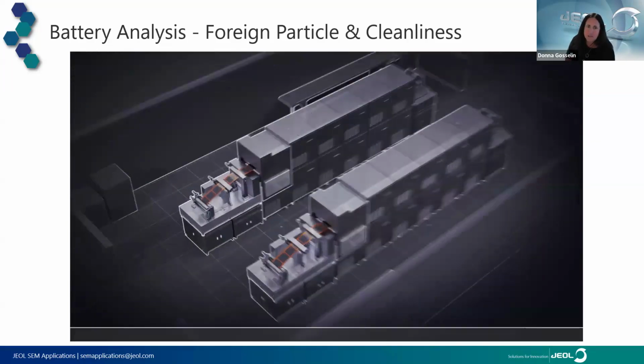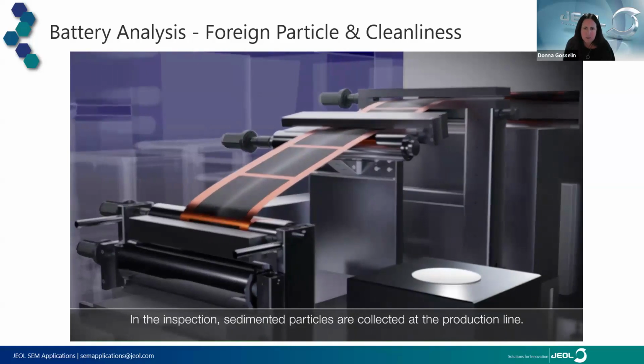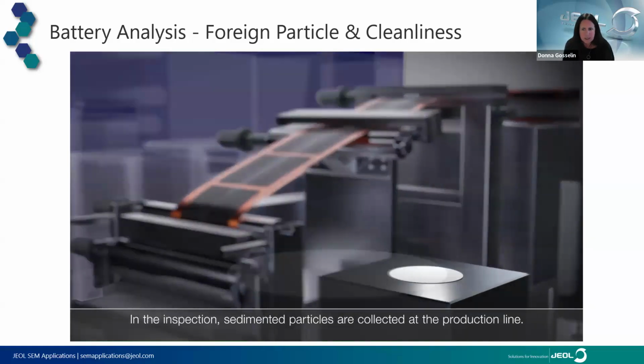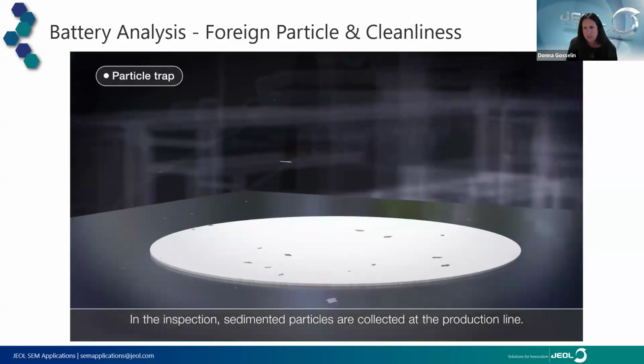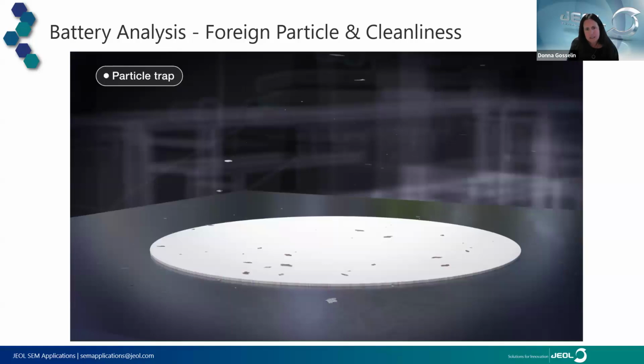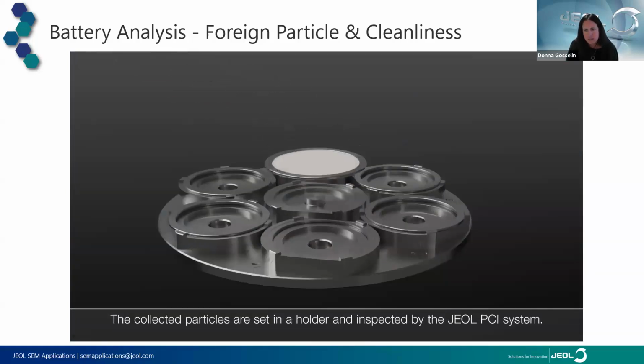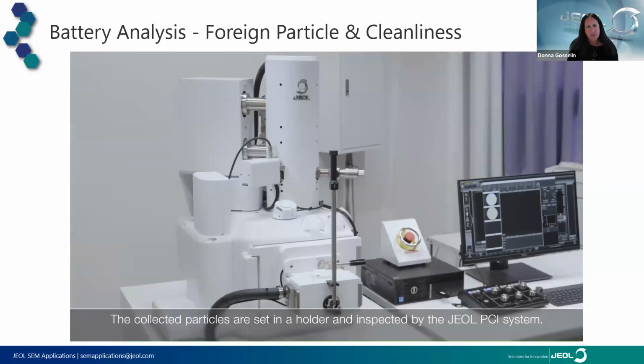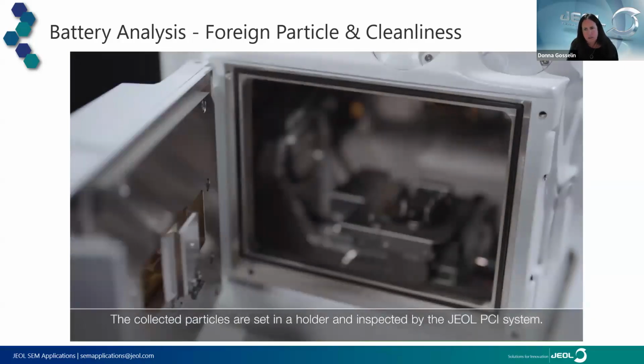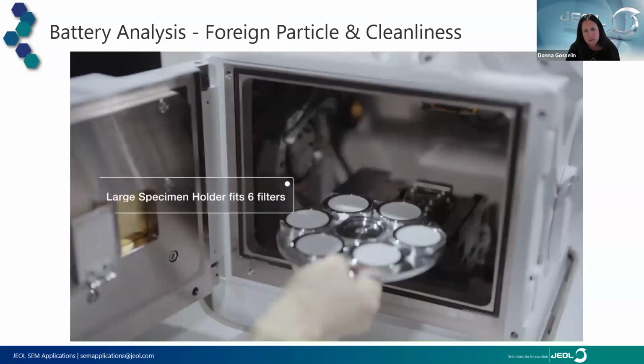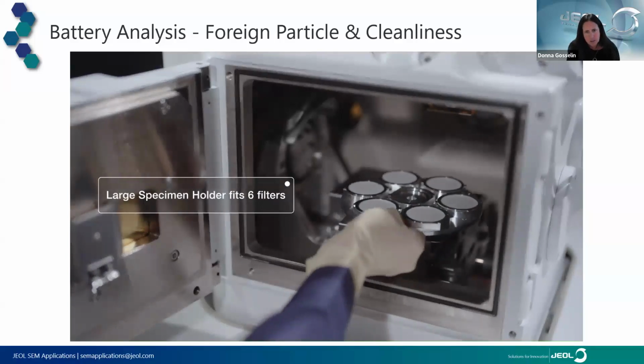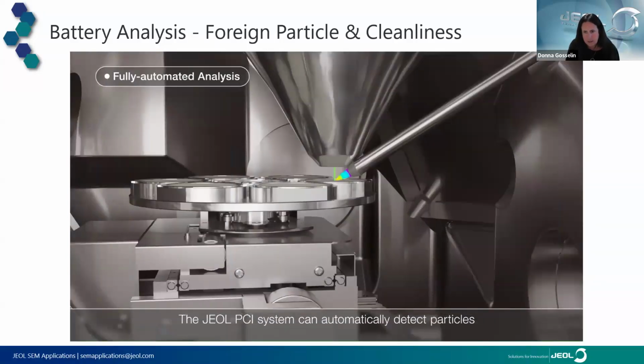So many automotive manufacturers have adopted the automotive cleanliness standard VDA 19.2, which originated in Germany, for looking at cleanliness in the production line. SEM is a great tool for implementing the measurement in this standard because not only can particles be detected down to the submicron scale, but chemical composition can be determined using our EDS elemental analyzer.